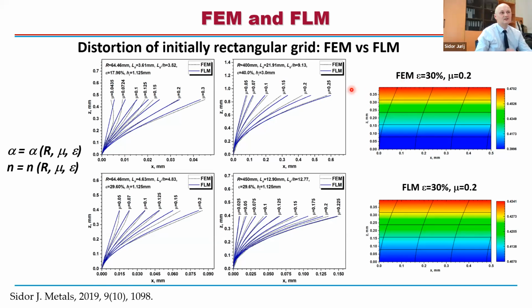So if you have an initial grid, which is rectangular, so vertical lines, right? And after the 30% deformation, you have deviation from this vertical behavior due to the shear, self-evidently, right? So as you can see, the same result could be nicely reproduced with the flow line model. So this one takes a couple of hours, this one takes a fraction of a second, 0.2 or 0.3 seconds.